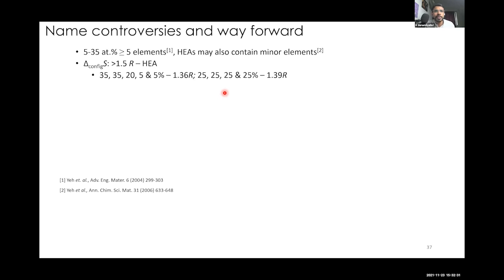Okay, so 5 to 35 atomic percent of more than 5 elements, and HEAs may also contain minor elements. This is how it was defined. And another definition was that the configurational entropy value should be more than 1.5 R. This I told in the initial slides itself. Now look at this. If we have 5 elements, 2 elements at 35, 35, a third element at 20, and the fourth and fifth elements at 5%. This is following the first rule, 5 to 35 atomic percent of 5 elements. But look at the configurational entropy value, it comes to 1.36 R.